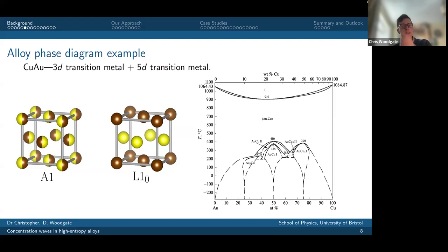So maybe a good take home from this is that just because the equilibrium phase at 200 degrees Celsius is this L10 copper gold phase, actually, if I take my alloy at 800 degrees Celsius, where I'm comfortably in the solid solution region, and I quench it down to room temperature, it probably is in the solid solution phase if I do that quickly enough.